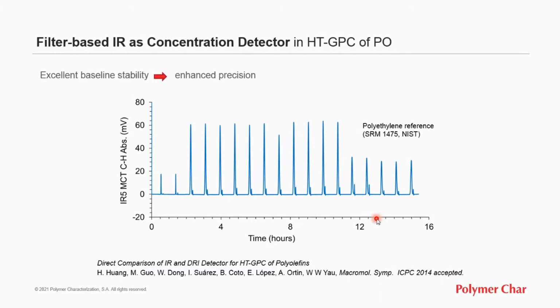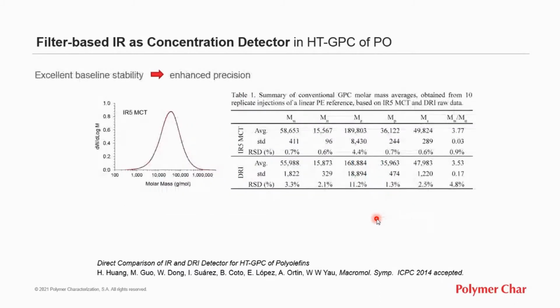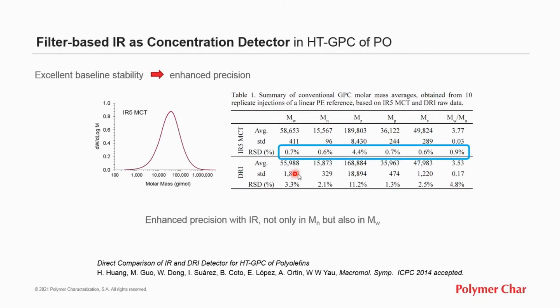This leads to enhanced precision in the molar mass distribution and also in the moments. Here we see 10 replicate analysis of a material by GPC with infrared. The relative standard deviation for number and weight average are around 0.6, 0.7, lower than 1%, which is quite good for high temperature GPC of polyethylene. And that was 3 to 4 times better than the results obtained by DRI detection in the same instrument.